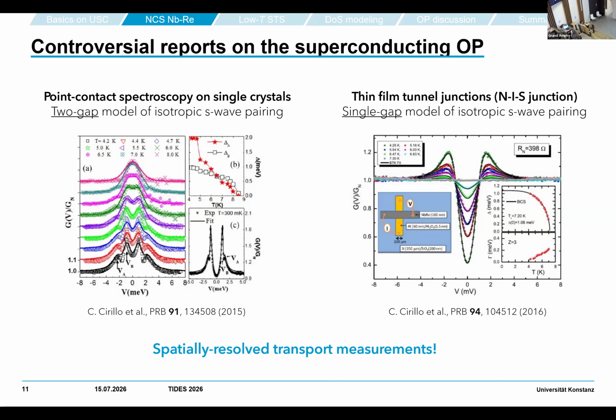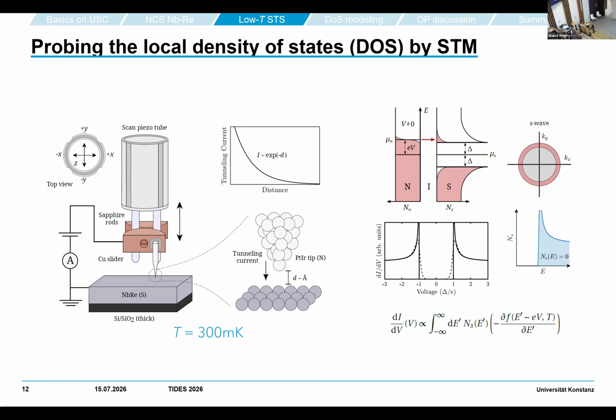So we need spatially resolved measurements to address this question, and this is now our experiment. We are doing STM at low temperature, using a normal platinum iridium tip, and this works at 300 millikelvin. We probe the tunnel spectra to learn something about the order parameter symmetry.